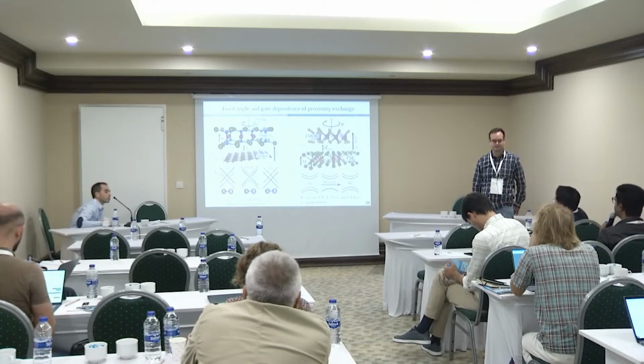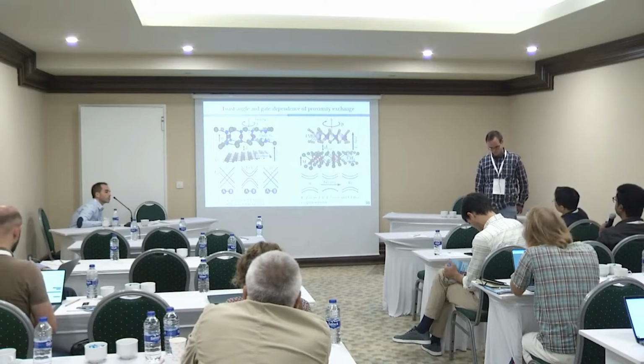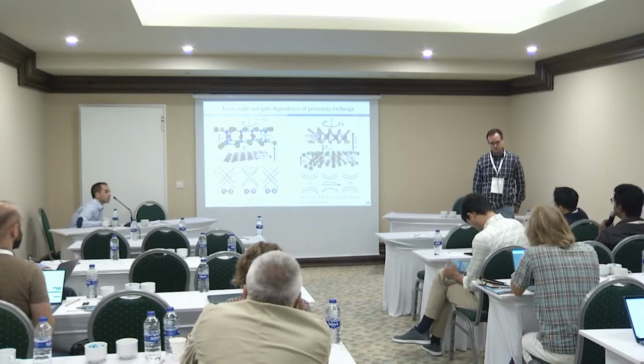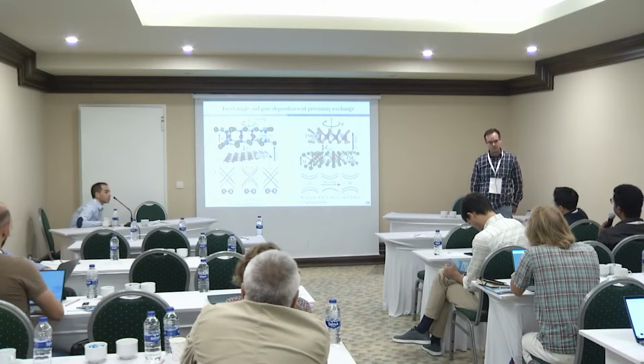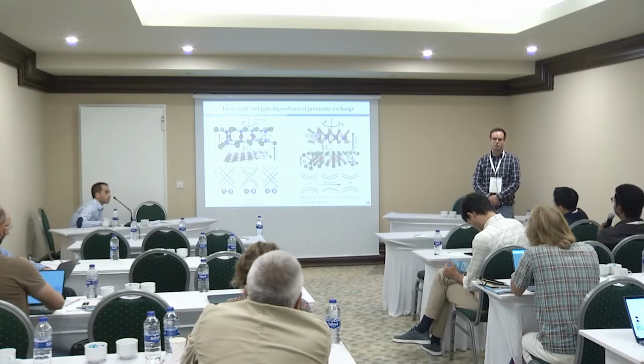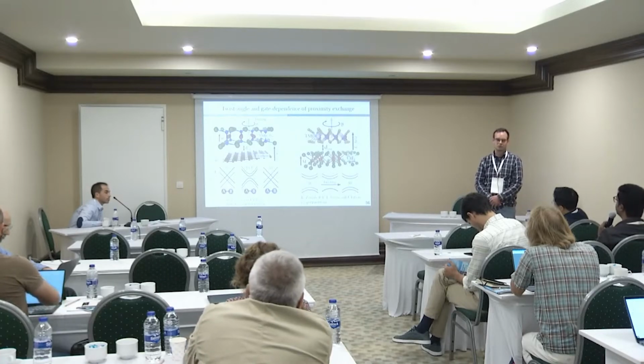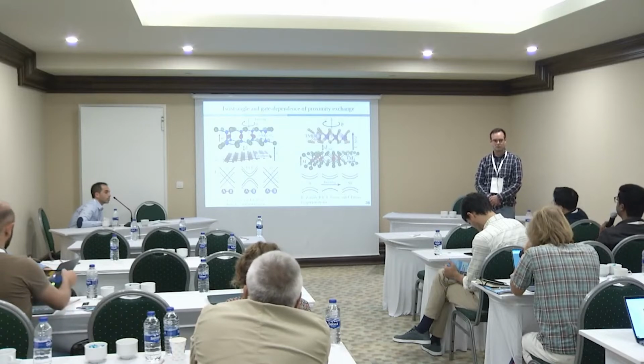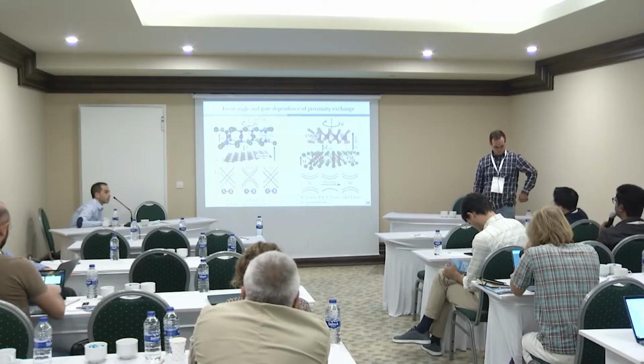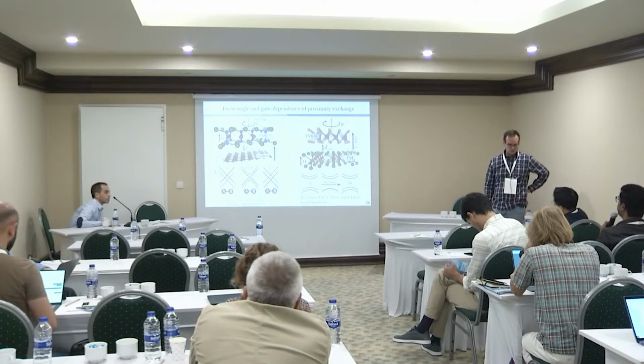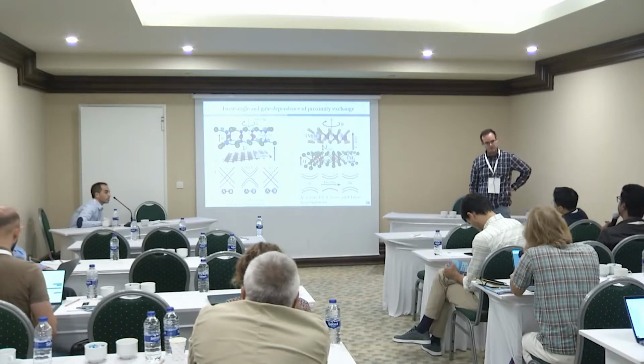So my question is, what will happen for monolayer graphene? If you put monolayer graphene on WSe2, what will happen? Because for bilayer graphene, we can understand that the bottom layer is in close proximity to the WSe2. That can enhance the spin orbit coupling for the bottom layer. For the top layer, since there is a van der Waals distance between the top and bottom layer, overall the spin orbit coupling is small. So my question is, what will happen for the monolayer graphene? Can it act similarly to the bilayer graphene? Can we switch the induced proximity effect? No.